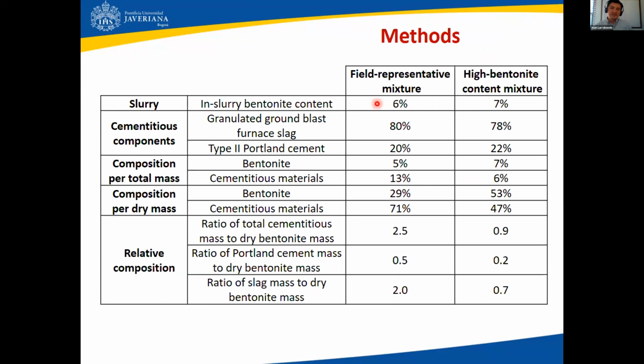So for the field representative mixture, again, this is typical of slag-CB wall construction. The slurry has a 6% bentonite content. And like I said before, the amount of slag replacement within the cementitious components is in the order of 80%. Of course, 20% Portland cement. You can compare side by side also with the high bentonite mixture. The composition per total mass is just 5% bentonite, because most of it is water, of course, and 13% the overall cementitious components.